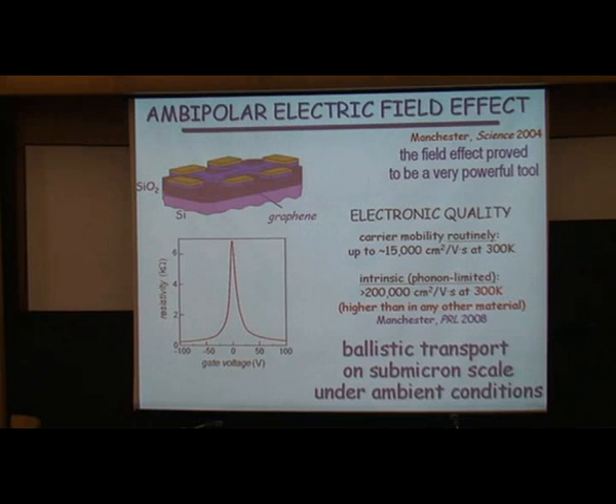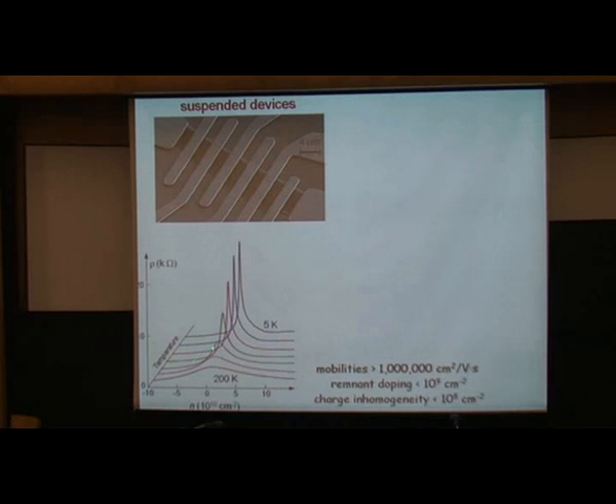When you get a high quality material, it immediately tells you that you can study a lot about this material. That's the latest result, where we try to improve quality even further. We suspended graphene on those fingers, and unfortunately it's essentially two-probe measurements, but it's suspended in air and annealed at 1000 centigrade by current, so all adsorbates and everything else goes off. In this material we again observe what I call the ambipolar field effect, and the curves look the same, but the scale is 100 times different. So it's much higher quality in terms of mobility. We reach what is typical for gallium arsenide structures. We don't have any doping and so on.